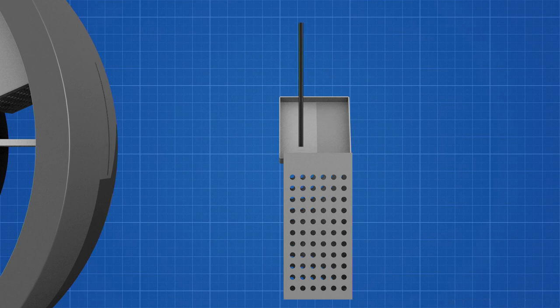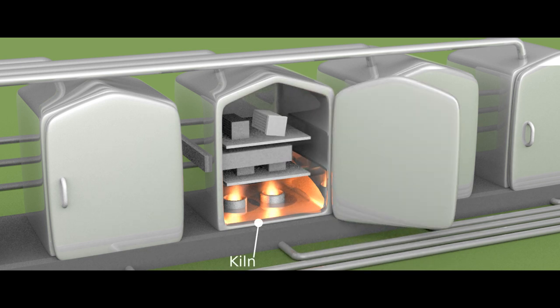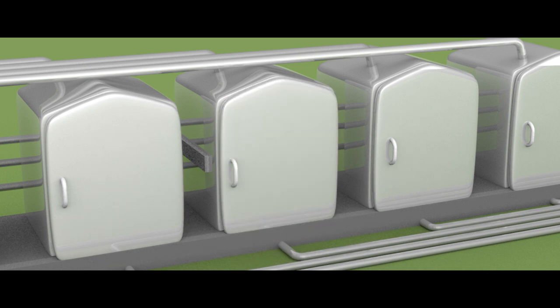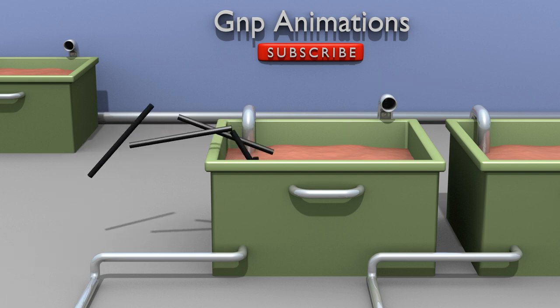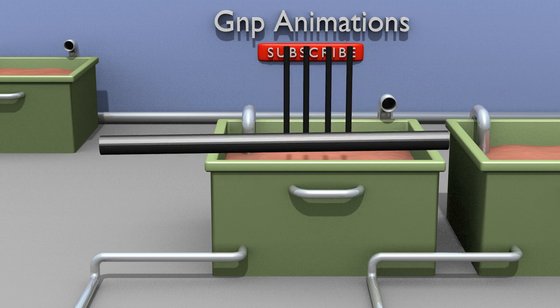But they're not quite strong enough. So next, they go into a kiln for 10 hours at 1000 degrees centigrade. This firing transforms the clay mixed with the graphite and turns the lead into their final hardness. Finally, resulting leads are dipped in molten wax which seeps into the tiny holes and allows for smoother writing. Finally, we made the pencil core or lead.